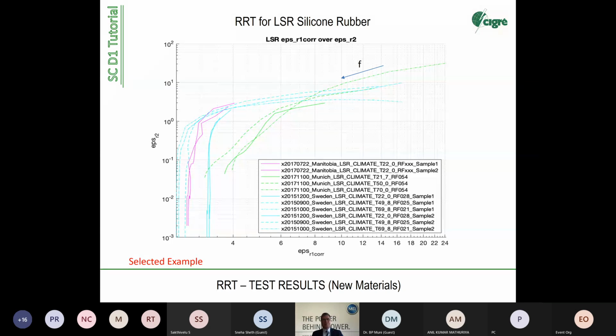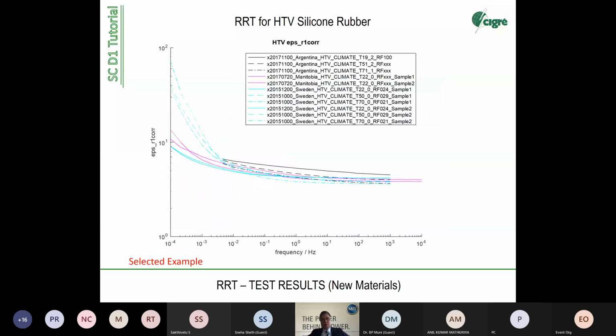This material here has, by material formulation, a higher amount of internal interfaces, just given by the filler loading, which may be between 50 and 60%. 50% of the elastomer is mineral filler. You can imagine how many interfaces you have between the fillers and the polymer when you think about that these particles are in the range of 10 to 20 micrometers. So these are areas of, I think, some soccer fields that you get in a small sample.